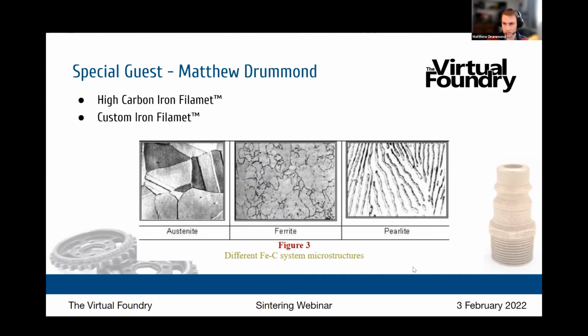Currently, the way I'm doing my testing is I'm testing these little flow rate cubes, I don't know if you can see them. I 3D print these cubes with the highest infill and the highest flow rate that the printer will put out, and that will increase the density of the part. From there, I put it in a furnace. I can tell you right now, I'm using a furnace that's not programmable. Please get a programmable furnace. It takes way too much time to use a non-programmable one.